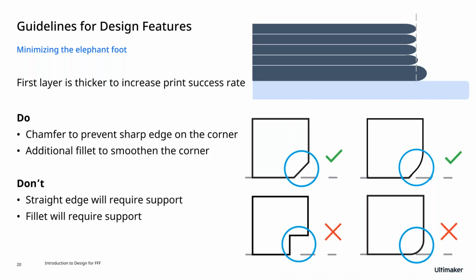Sometimes when printing without a raft, you may notice that the first layer is slightly larger than the rest. This is due to a phenomenon called elephant's foot. While rarely noticeable, it decreases the tolerance of functional prototypes. A simple solution to fix this is adding a 45-degree chamfer on the bottom edge of the print. The effects of elephant's foot can typically be negated with this.